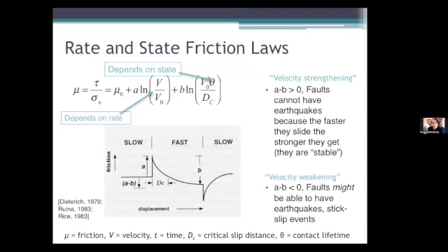And so this is a rate and state friction law, where, many years ago, it was observed that the friction is not just a first order response; you also have a second order response where it depends on the velocity that it was at, if you have a velocity step where it goes from one to the next, and it also depends on state, this characteristic of the interface.